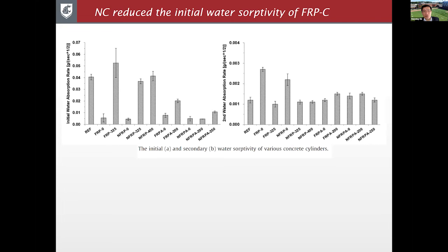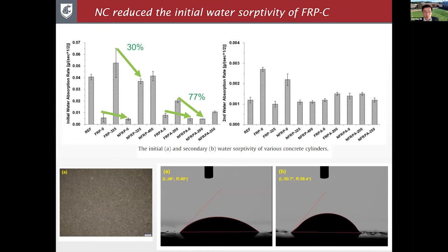Now, if we measure the quantitative initial water absorption, which is the first stage on that curve, corresponding to how fast moisture is moving into the microcracks and the pores, you can see in some cases, especially for the pre-aged group, you are seeing 77% reduction, which is highly desirable for the durability of the concrete. And even for the new ones, you're looking at 30% reduction by this 1.5% nanoclay. However, if you look at the secondary water absorptivity, there's no significant difference because that's more how fast you fill up the air voids.